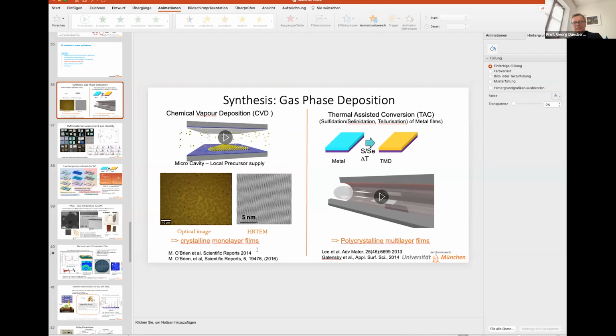We are just about to publish a very full study using DOE, design of experiments, for tungsten sulfide growth, where we actually were able to tune this towards different properties: full layers, multi-layers, and closed layers versus flakes. But it also depends a lot on the geometry of your setup.